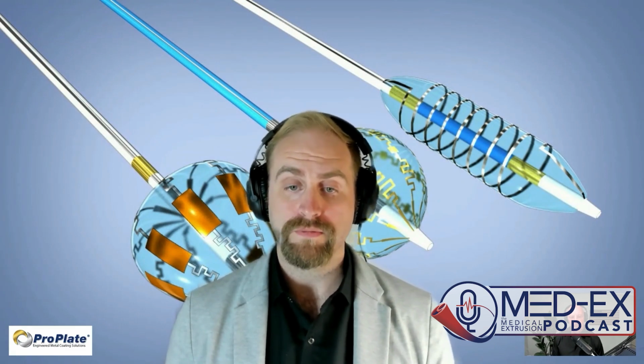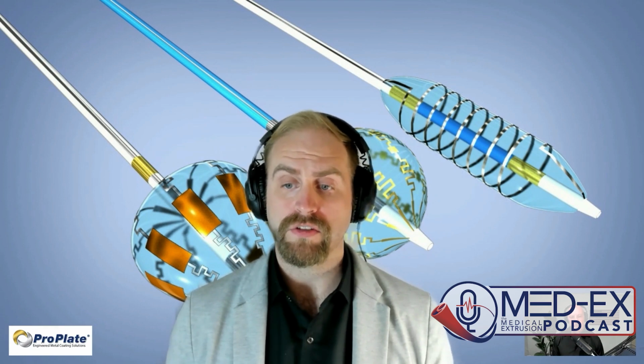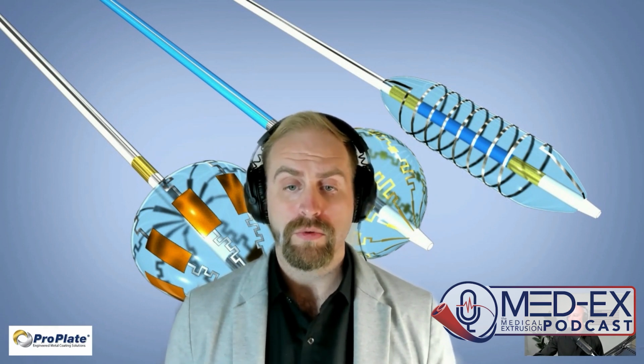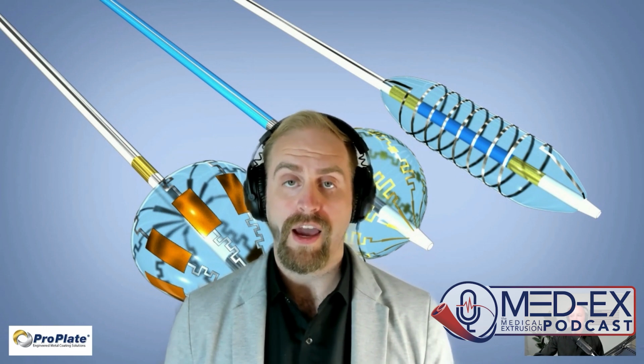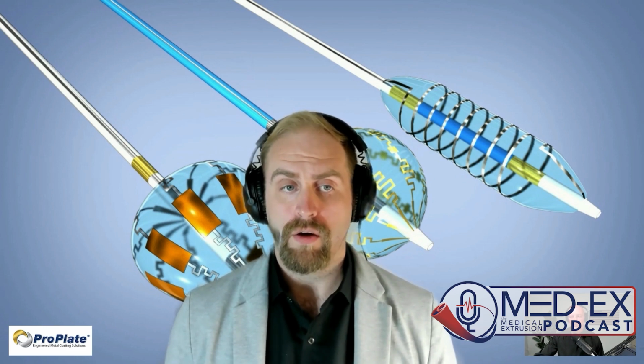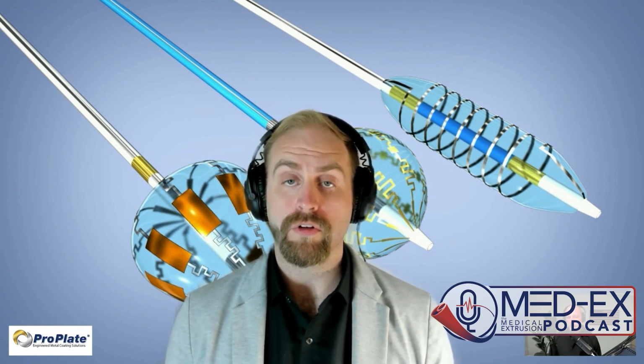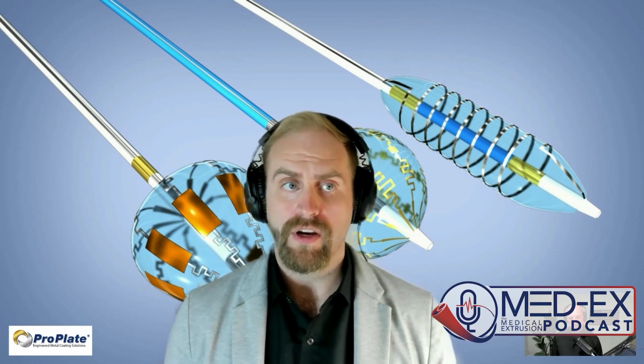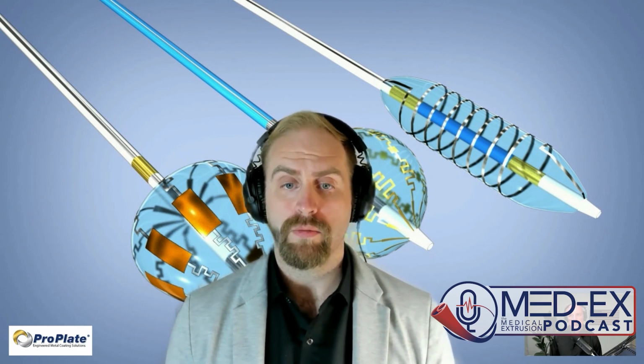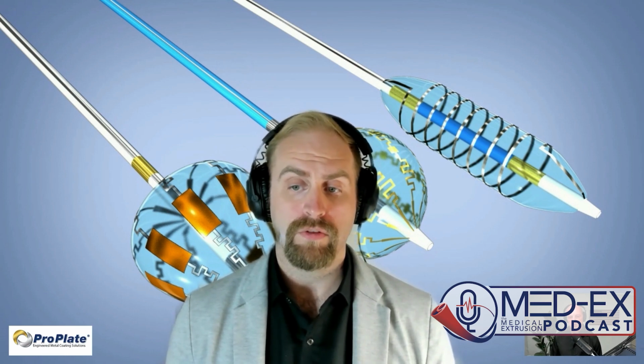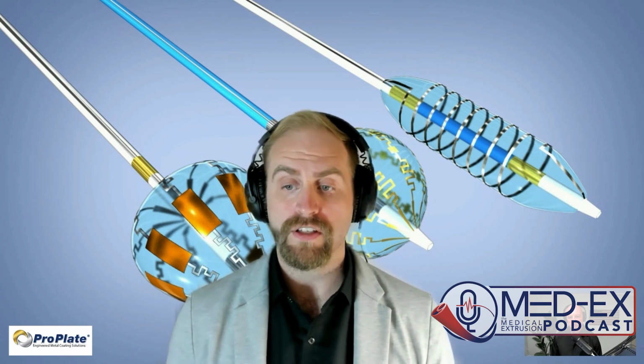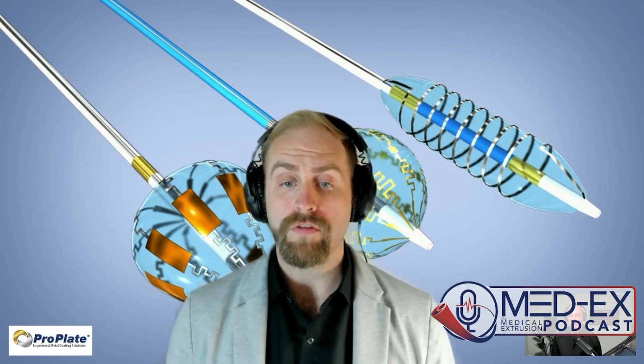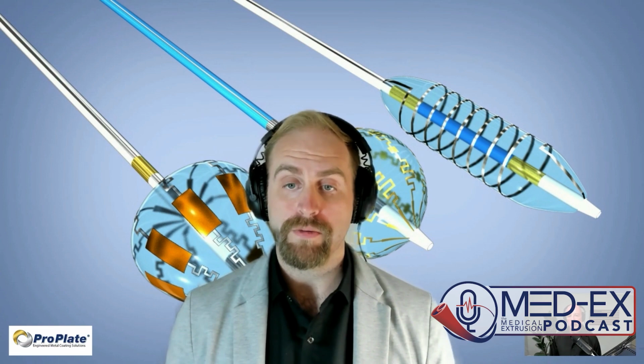But there's several other advantages to using a plated marker band with our Vizi-Band process versus a traditional marker band. We can also reduce the profile because we're using an additive process to create the marker band. We're not really limited in terms of thickness, with the exception of what shows up bright under fluoroscopy. Those typically range between 0.2 to about 0.8 of a thou that our customers find adequate radiopacity, but we don't really have a limitation on the upper end of the thickness. We can plate several thousand of gold and up to 1 thou of platinum.